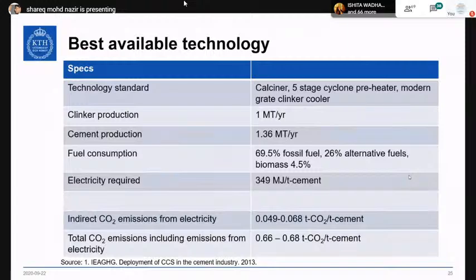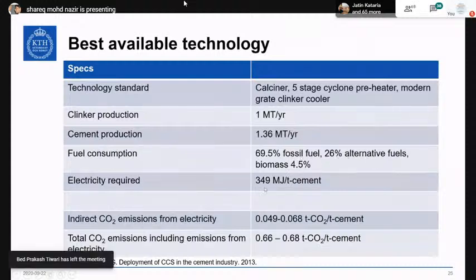If we speak about the technology that we saw in the picture, it is calciner, 5-stage cyclone preheater, modern grate clinker cooler. We have clinker production of 1 million tons per year, cement production 1.36 million tons per year. The fuel consumption is 69% fossil fuel, which is basically coal, 26% alternative fuels, and biomass 4.5%. The electricity required is 349 megajoule per ton of cement. Indirect CO2 emissions from electricity is around 49 to 68 kgs per ton cement. And then total CO2 emissions is around 660 to 680 kgs per ton cement, or 0.66 to 0.68 tons CO2 per ton cement.